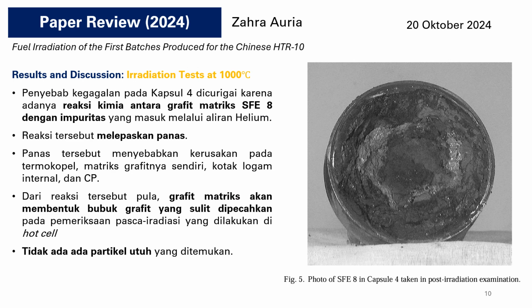The failure that happened to Capsule 4 was suspected to be due to a chemical reaction between the graphite matrix of SFE 8 and the impurities that flowed in through the helium flow, and that reaction released heat. The heat caused damage to the thermocouple and the graphite matrix itself, as well as the internal metal box and the coated particle. From that reaction, the graphite matrix formed graphite powder that is hard to break, and that hindered the post-irradiation examination carried out in a hot cell. As we can expect, there was no intact particle found.